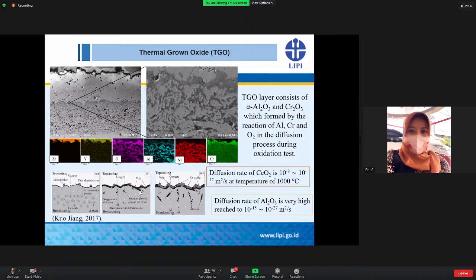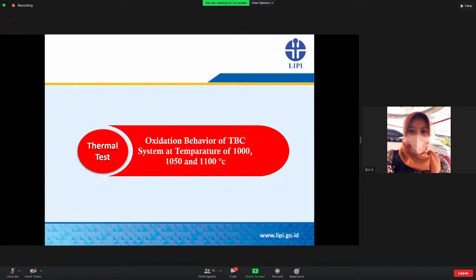And when thermally exposed for a long time, the appearance of beta nickel aluminum precipitate occurs and makes the aluminum diffusion decrease. So finally, chromium oxide forms on top of the continuous alumina scales, as you can see in these figures, and at the same time, the precipitation of internal oxide of alumina occurs underneath the TGO layer. So in order to clarify the oxidation behavior, the TBC system will be further evaluated by increasing the exposure temperatures to 1000, 1050, and 1100 degrees C.